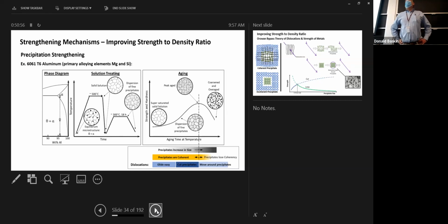Why do you want it to be at that critical size so that you get some dislocations that wrap around and some that cut right through? Well, there's some threshold where the amount of energy gets so high to move the dislocation that it takes less energy just to wrap around it. But the point is, you're just trying to get to that point where it's harder and harder and harder. It takes more and more energy to move it, just to that threshold where it'll start looping around instead of cutting. Gotcha. So you're just heat treating to that point where it's that last little bit of energy to cut through versus looping around. That's where you meet the optimum strength of the material.